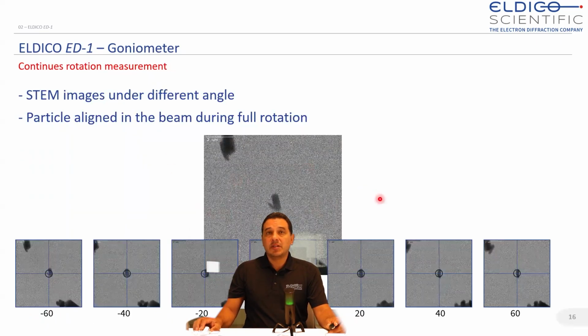Now let me show you how precise our system is on a rotation. This is STEM mode, so we have a particle which is approximately, I would say, 500 nanometers in length here. And you see that at the different angles, going from -60 all the way to 60 in this case, the particle remains always centered. This is because our system has been optimized for that. So when we collect the diffraction and we do the continuous rotation, basically the particle will remain in the center for the rest of the time.